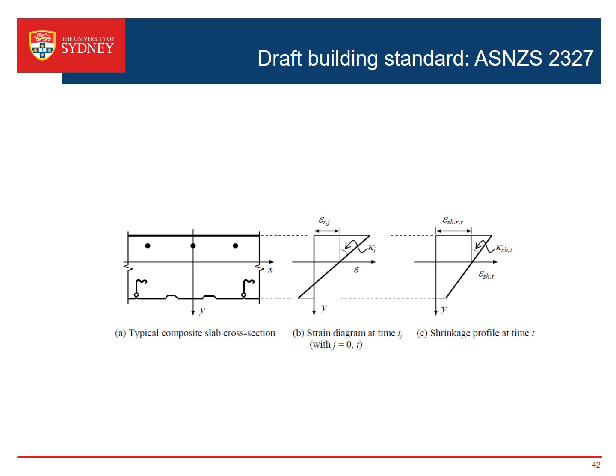So what John Leake has been able to find is that we actually get this non-uniform shrinkage throughout the depth of the slab, and many people thought originally, certainly when we look at concrete filled columns, there's a beneficial effect. But when we're looking at composite slabs, it's actually a detrimental effect, because you get high shrinkage at the top, low shrinkage at the bottom, you get a net, if you like, moment which is actually going to increase the deflections in the slab. So in fact this work was originally funded by the decking industry. They weren't entirely happy with the outcome, but the reality is we've got to reflect what actually happened.